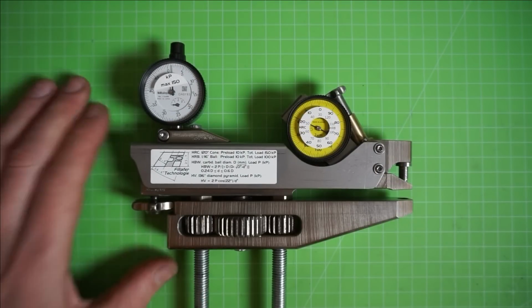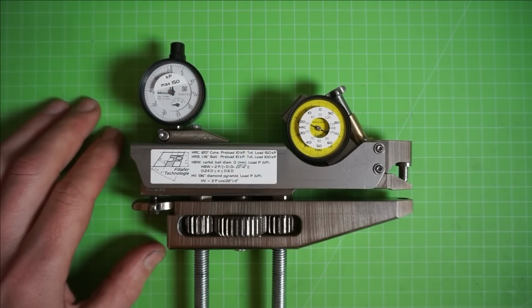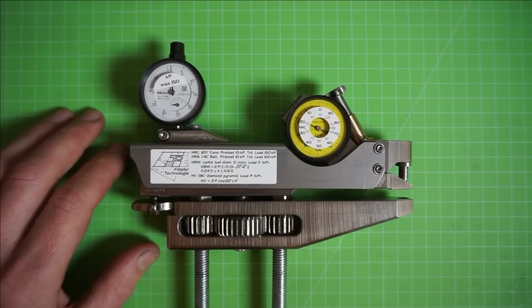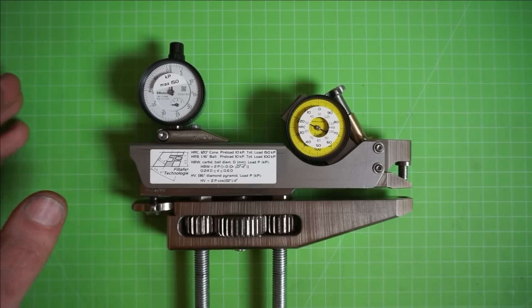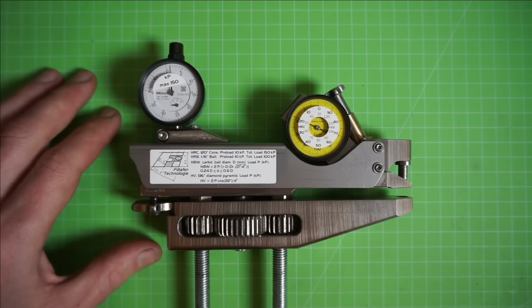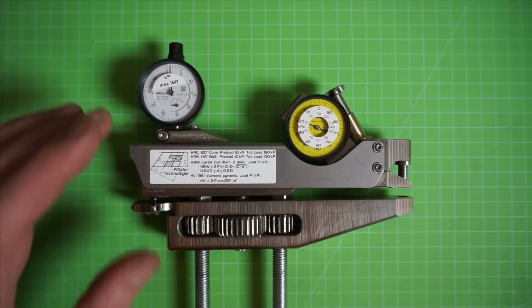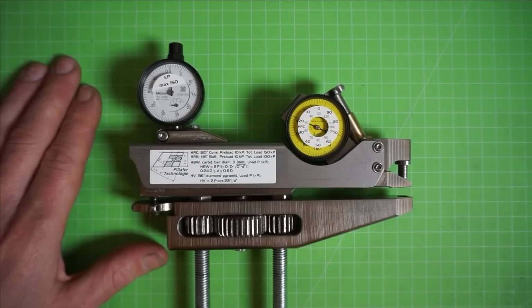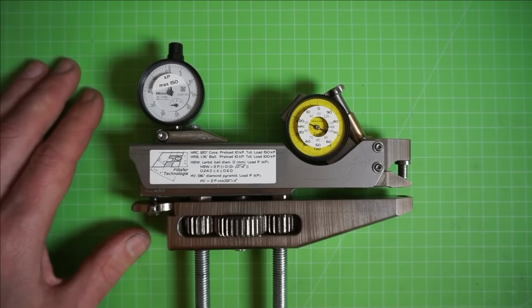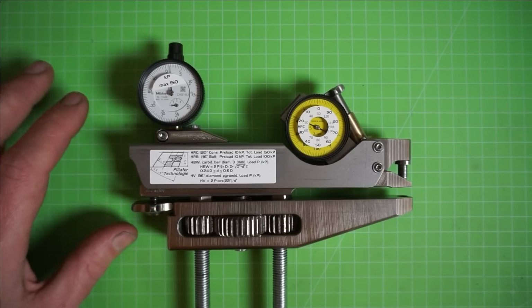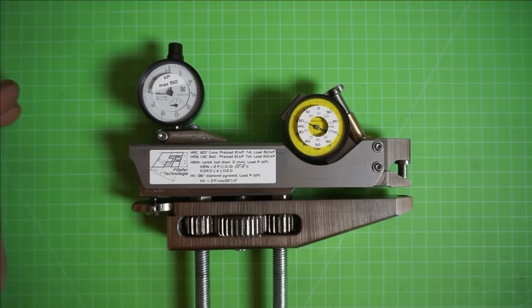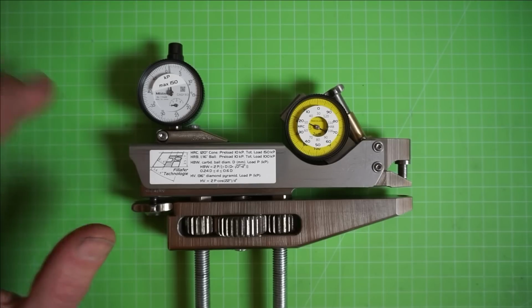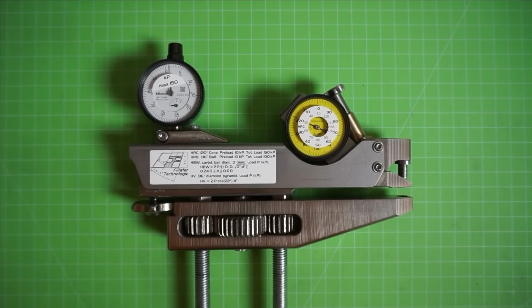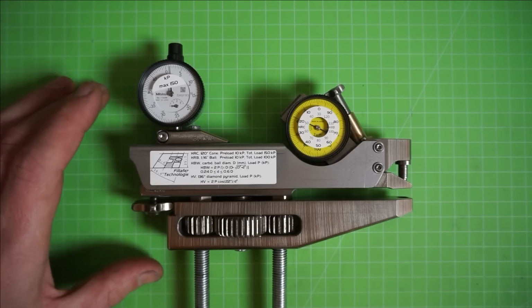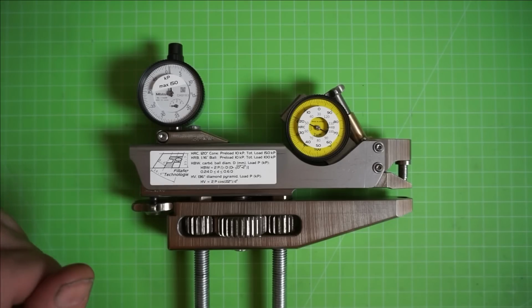So far so good. The only problem with the Rockwell hardness values or the Rockwell testing procedures is that they do not translate proportionately into material strength. So twice the Rockwell hardness does not necessarily mean twice the material strength. There is a certain nonlinearity. If you're interested in material strength and use lookup tables available to translate from Rockwell to strength, then you should be fine. However, just for the gut feeling and for shop use, it may be misleading to just use Rockwell if you're interested in the material strength.